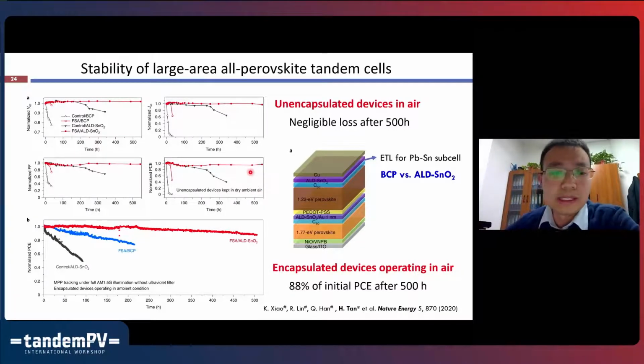We also measured the MPP stability of these devices, encapsulated with epoxy and a glass slice. We found that with this molecular passivation and also with this atomic layer deposited tin oxide as the ETL, we can much improve the operational stability of these devices. The device can maintain almost 90% of their initial efficiency after 500 hours of operation.